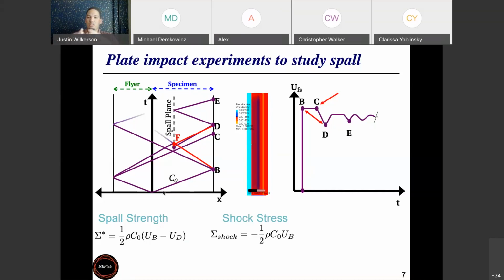And so essentially by the time spall failure occurs, you have a material that's gone through a compressive cycle first. And so it's a totally different material than it was in its pristine condition. So you have to take that into consideration. And so we always want to report and know what the shock stress was in a spall experiment.